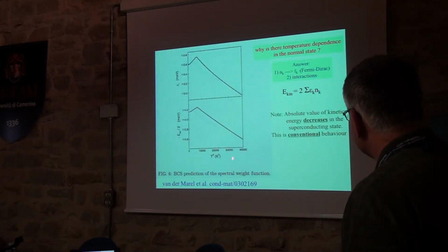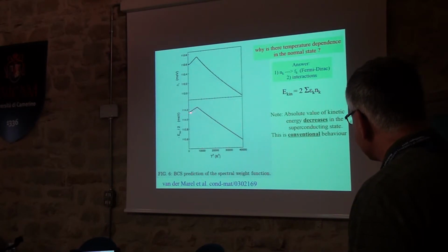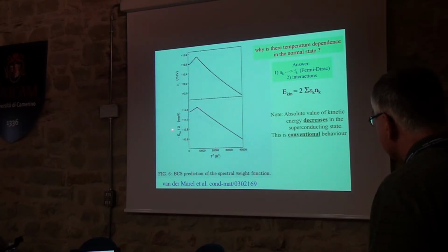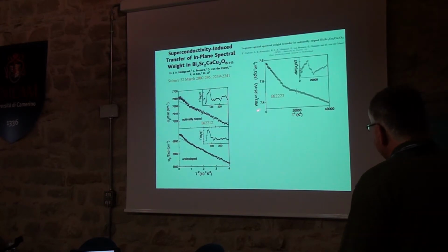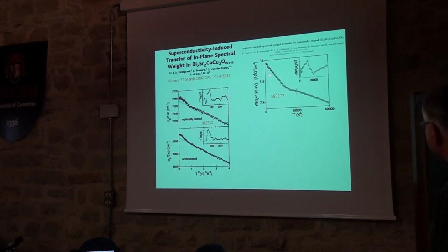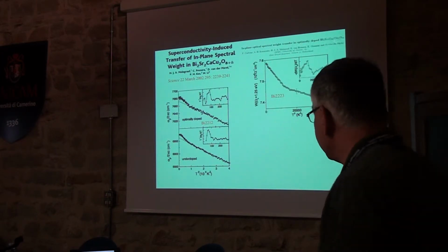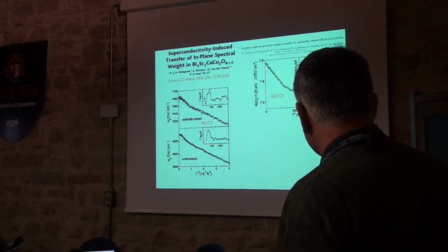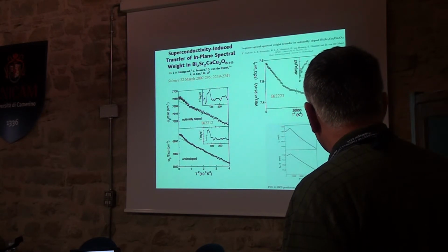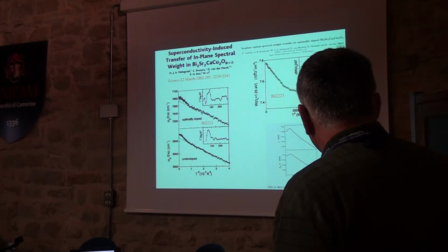But the plot of the electron distribution function in the superconducting state was smeared out as opposed to the normal state, just like it's smeared out in the normal state because of temperature. So this goes back. When you look at experiments, these are original ones, and this is one from 2006, I think. Here's Tc, and instead of coming down, like I just showed you, it goes up. Okay, and this was a sign that that paradigm I described from BCS theory seemed to have something wrong with it.